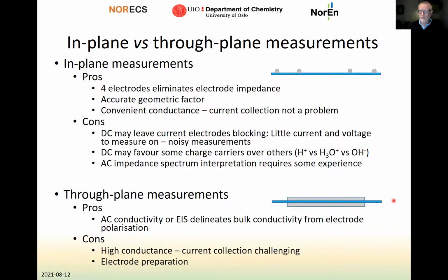On the other hand, if you do a through-plane measurement, the nice thing is that with impedance spectroscopy or AC conductivity, you can delineate the electrode impedance from the bulk impedance by deconvoluting the impedance spectrum. So that is nice. But on the other hand, you will have a very high conductance because the membrane is very thin in this direction and the electrode is big. So you get a challenge in collecting the current properly through the in-plane conductivity of the electrodes. And you also have to make the electrodes properly in order to measure like this.